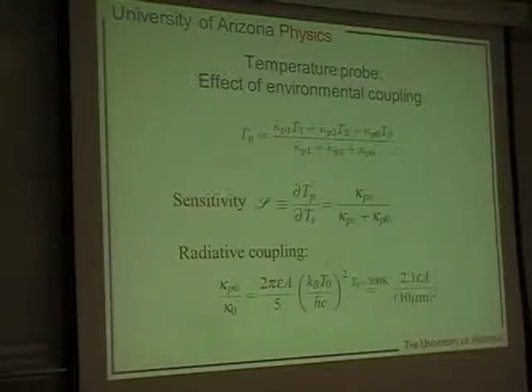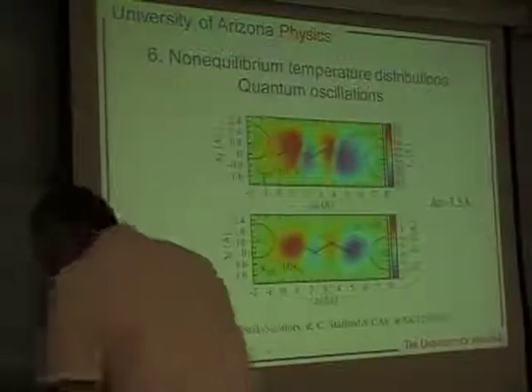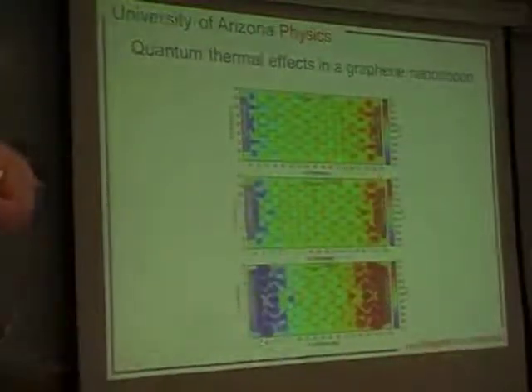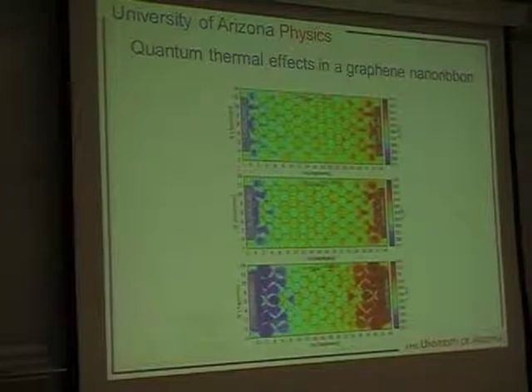But that brings up a good point, that in these systems out of equilibrium, which don't have a very strong coupling between the different degrees of freedom, this is the electron temperature. The phonon temperature would be entirely different in this system. There's no reason when a system's out of equilibrium that the different degrees of freedom have to have the same energy distribution. So the temperature of the phonons in the system would not be the same as what I'm showing here. But because we have this probe in the tunneling regime with a vacuum tunneling gap, we believe that the dominant thermal coupling will be via tunneling of electrons. Of course, if you go into the contact regime, you're going to couple with the phonons as well. And we have considered that also, but I don't have any figures with me to show you. But essentially, the phonons, because their wave properties are not correlated with those of the electrons, give a background similar to the environmental coupling. That's what we predict anyway.